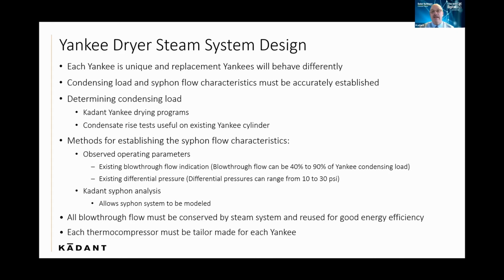And if it's a case where you're replacing a Yankee or increasing the conditions, or it's a new Yankee, we have modeling software that we can run through and determine what that condensing load should be theoretically. From there, we go on to the blow-through calculation. Once we know the siphon parameters and we know the condensing load, the difference is going to be the blow-through. And the blow-through in a Yankee can be anywhere from 40 to 90%. Even, I've seen some close to 100%. So that blow-through amount can vary substantially.